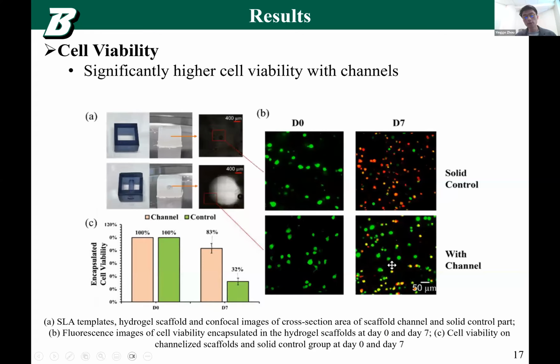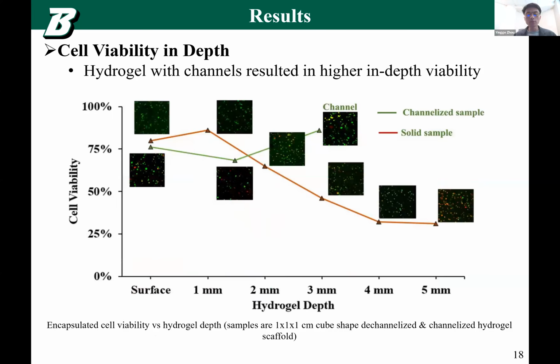And then if the hydrogel has a channel, then the cell viability in the center of the hydrogel is pretty high, because on the surface of the hydrogel, they can contact the cell medium. So the cell viability on the surface is no problem. The problem is in the center of the hydrogel. Even though the hydrogel is also a porous structure, there are not enough pores for the cells to live. And that's why we need the